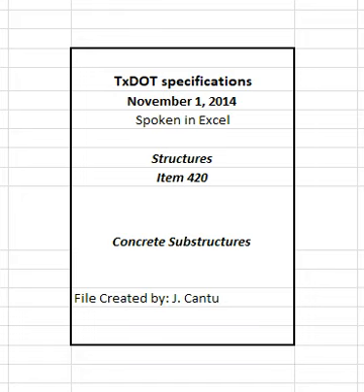Use tremies that are watertight and of large enough diameter to allow the placement of the concrete but less than 14 inches in diameter. Construct the tremie so the bottom can be sealed and opened once the tremie has been fully charged with concrete for underwater placements. Use pumps with lines at least 5 inches inside diameter, ID, where grade 2 or smaller coarse aggregate is used, and at least 8 inches ID for grade 1 coarse aggregate.